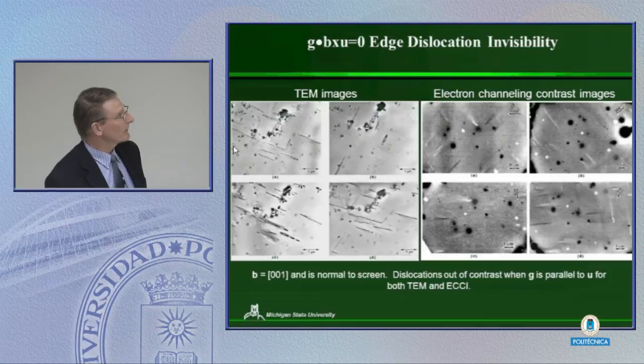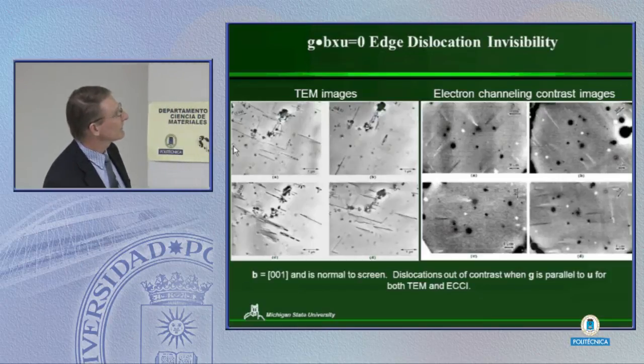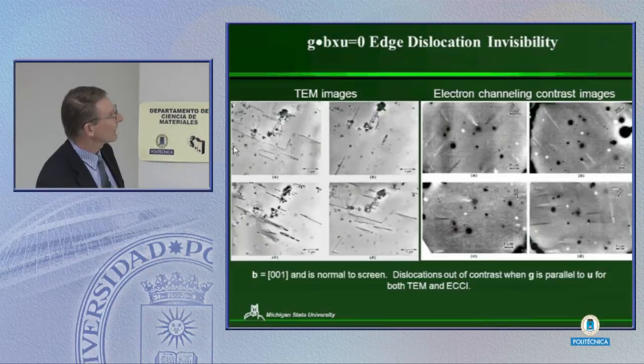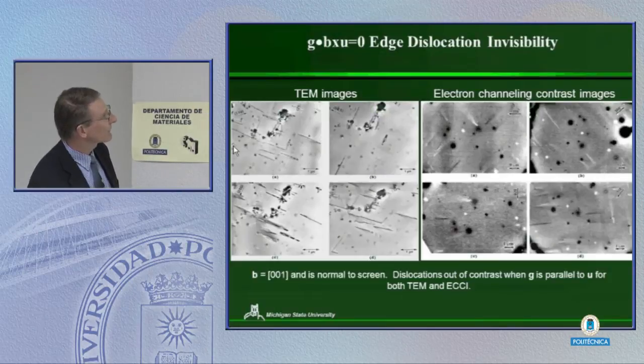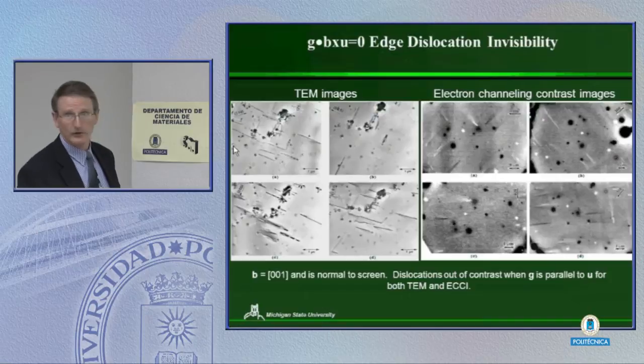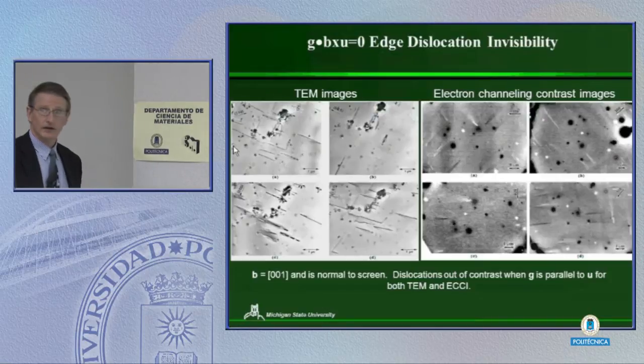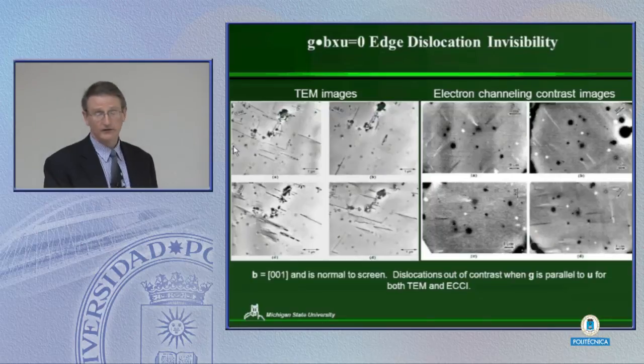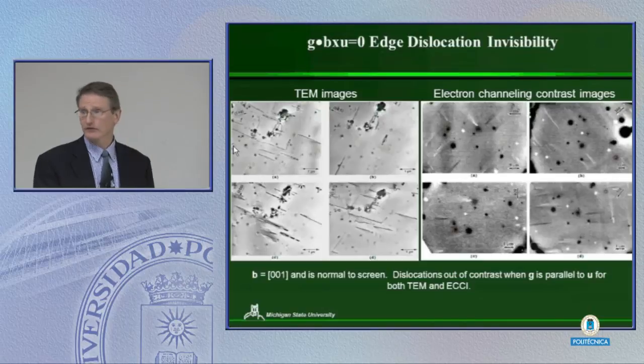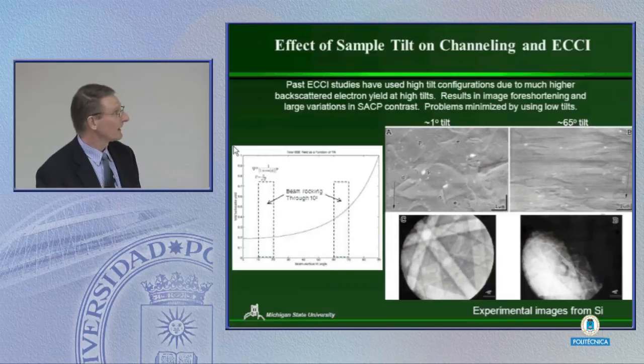When we go over and we do the same thing with the channeling conditions, we can see that in this image we get segments that are both light or dark, that are both in contrast for these 110 type reflections. But when we go to these 200 reflections, we see only one direction is visible. So again, the same criteria hold. And so that means that if we're very careful, and it's very tedious work, I'll be honest, my students don't like doing it, but we can determine things like Burgers vectors, and we can certainly determine things like line directions through trace analysis, rather than having to make a TEM foil to do those things. And again, sometimes that's a valuable thing to do.